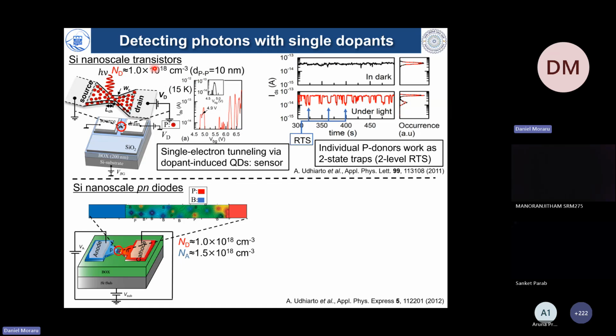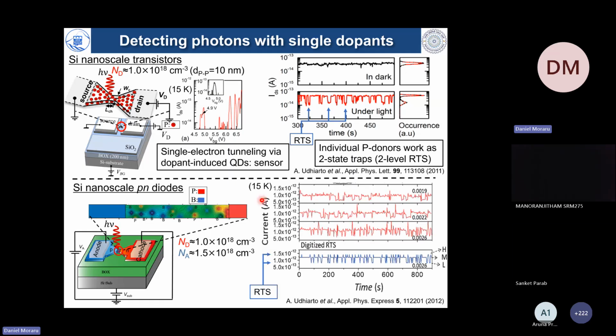Now, at similar low concentrations, but in p-n diodes, with both concentrations in the order of 10 to the power 18 per cubic centimeters, we should think very clearly about the atomistic distribution of the dopants again. Boron and phosphorus dopants can modulate the potential very dramatically. Now, if you irradiate light on these devices, we can see a different type of random telegraph signals. They are multi-level signals. In fact, if you look at some of the digitized RTS, it's a three-level signal with a low, medium, and high level quite clearly visible. This Applied Physics Express paper explains how this is related to trapping in a phosphorus and trapping in a boron atom almost simultaneously. So this is why we are seeing multiple level RTS.